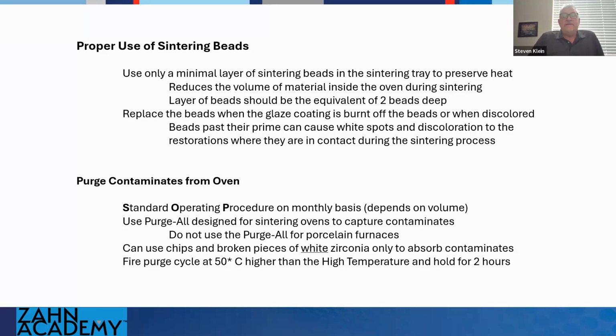You would use a material, and we sell it at Zahn here, called Purge All. It's designed to work kind of like a sponge. When you heat the oven up, it soaks up all of those contaminants, and then you just throw it out and continue to do another batch until you see them come out clean and white. And be careful. There is a Purge All for porcelain furnaces, as well as the one designed for sintering furnaces. Make sure you get the sintering furnace version. If you use the porcelain version, you'll get a tray of pretty glassy looking stuff coming out. The temperatures are not the same, so there is a difference.